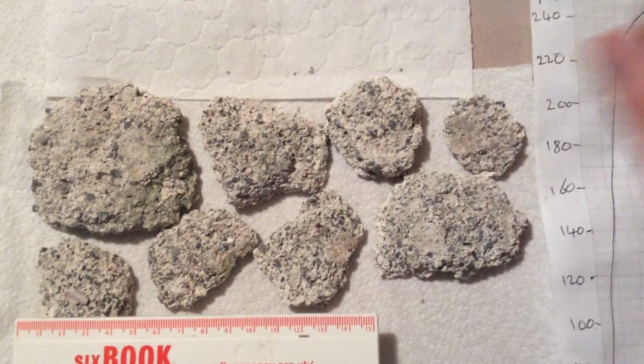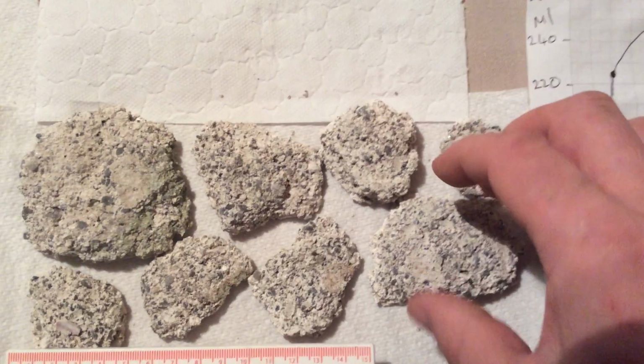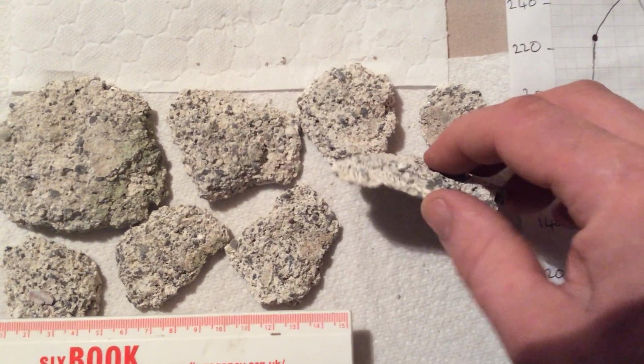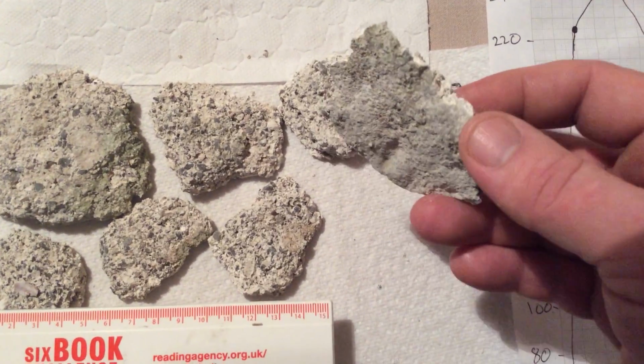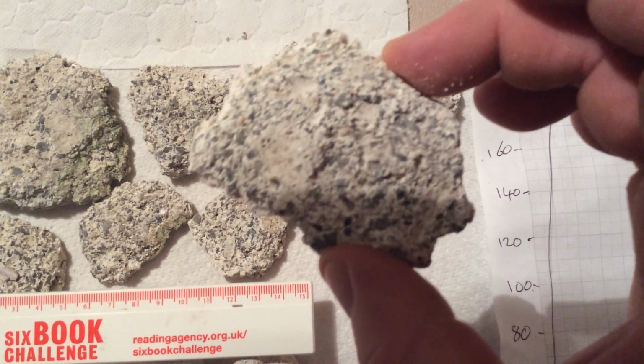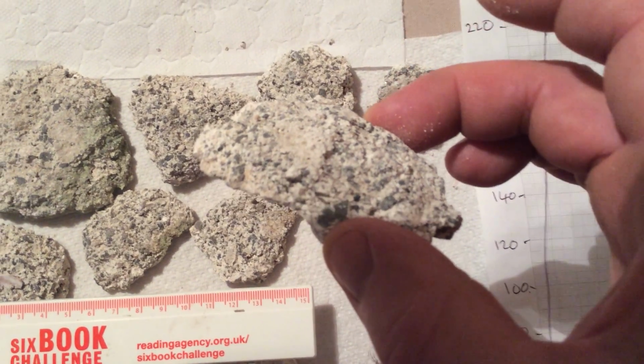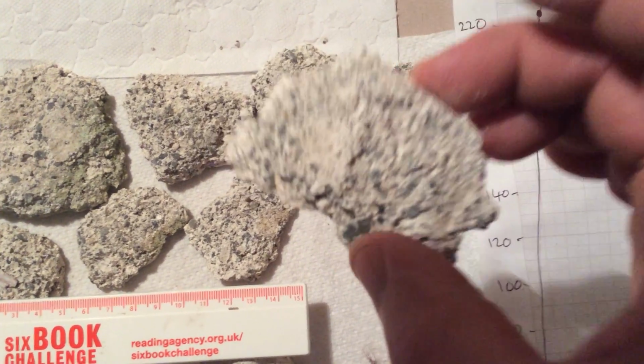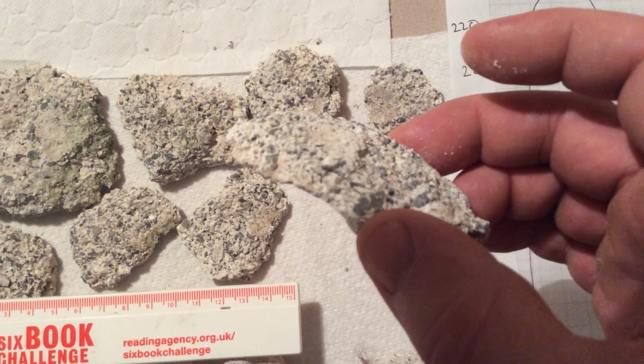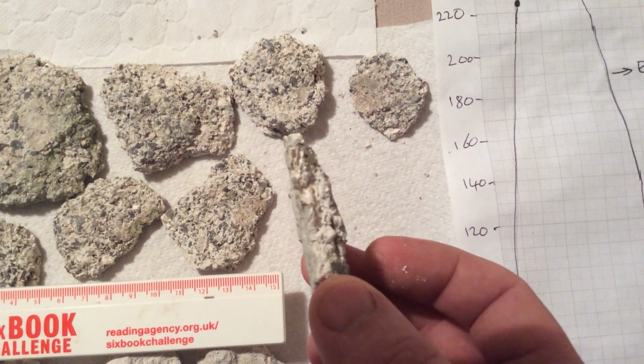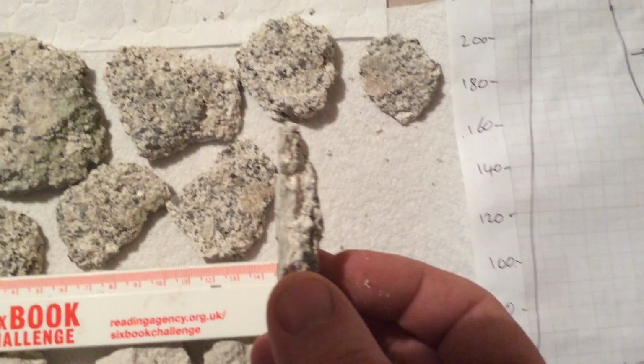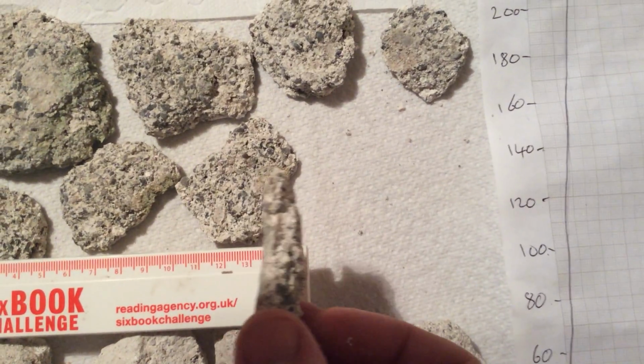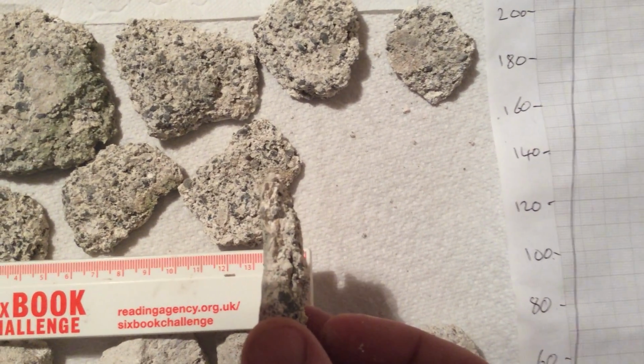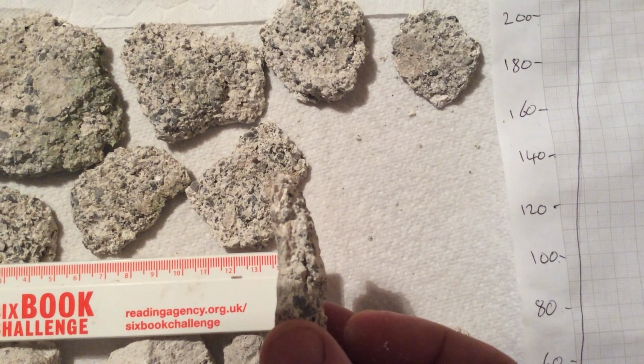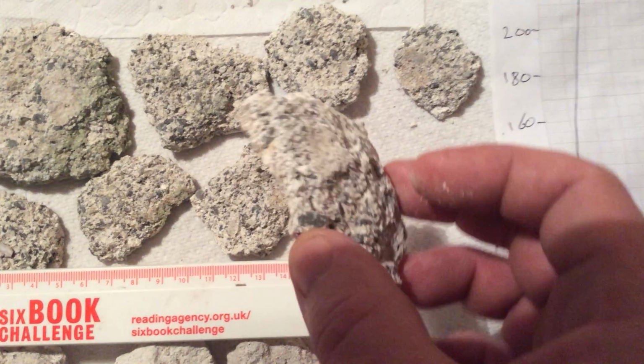When we look at the material, we see a lot of porosity in it. It's quite low density, and it sort of naturally falls off the building at about thicknesses of about 15 millimeters.